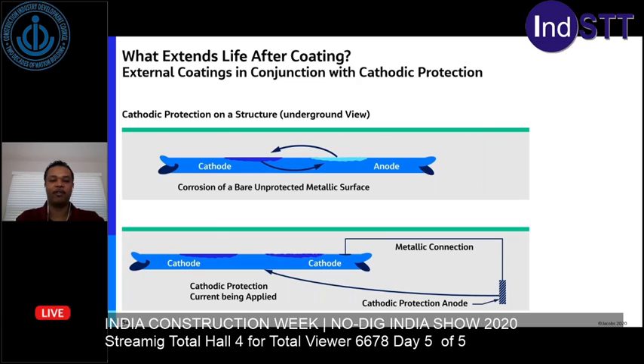So what extends the life after the coating? Well, cathodic protection. The photo on the top shows an unprotected metallic structure that doesn't have any cathodic protection. That particular pipe has both cathodic and anodic regions on it. Those areas are constantly interchanging, and that structure is trying to release the energy to get back to its natural source, which is iron ore.